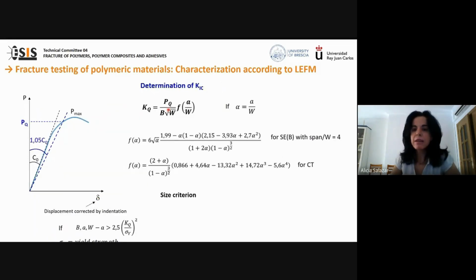KQ is calculated using this expression. Apart from PQ, B is the thickness, W is the width, and F is a calibration factor dependent on the crack length to width ratio, alpha. This slide shows the calibration factors for the 3-point bending specimen with a span to width ratio of 4 and for the compact tension specimen.